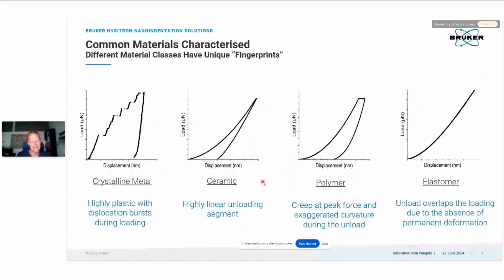But the most important thing is that we are penetrating into the material and we are collecting load and displacement data. And if you look at these indentation curves on the different materials, you might already get the idea what the material is about. So if you look at the crystalline metal, you see the discontinuities that are related to the plastic deformation. So we see some elastic deformation in the beginning, and then this material starts plastically deforming. The other materials have a different shape of the unloading segment, which results in a different value of an elastic modulus.